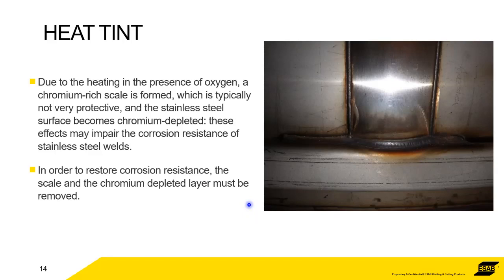So in real life, photograph of welding of stainless steel, I believe this was duplex, you can see quite clearly that in the heat affected zone you've got very serious heat tints. So very dark, getting lighter and lighter. So the darker area has obviously been hotter. As you move away from the weld, then it's getting slightly cooler, but it's still a heat affected zone. So that means that this area of the base metal has obviously got chromium oxides on the surface, and then immediately underneath you've got a chromium depleted layer. So that really is going to affect the corrosion resistance of your stainless steel.